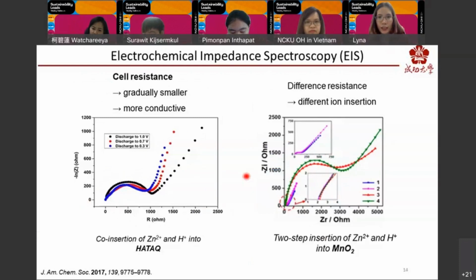Here are the EIS results. During the discharge process, the manganese oxide material was reported with two-step insertion of proton and zinc ion with significant difference in resistance. In our case, the cell resistance appeared to be gradually smaller. This most likely means that the more zinc and proton ion interact with HATAQ, the more conductive the structure becomes. This analysis provides strong evidence for co-insertion into the HATAQ cathode material, which is very important in the mechanistic study.